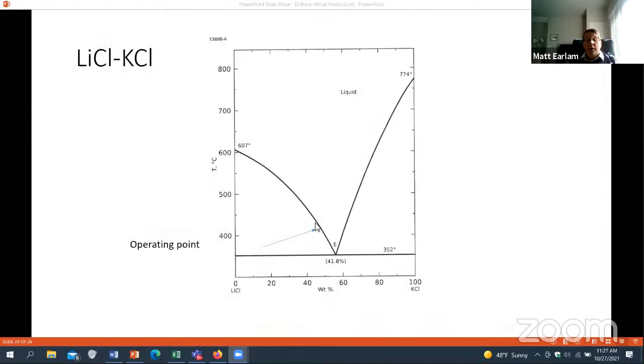We operate at this kind of operating point. So you can see here's the eutectic diagram, here's the phase diagram, potassium, lithium chloride. We operate at about this point, a little beyond the eutectic, a little more lithium rich. But you can see there's a big melting point reduction from the lithium salt, which is at 607 down to 352. So you really want to operate here.